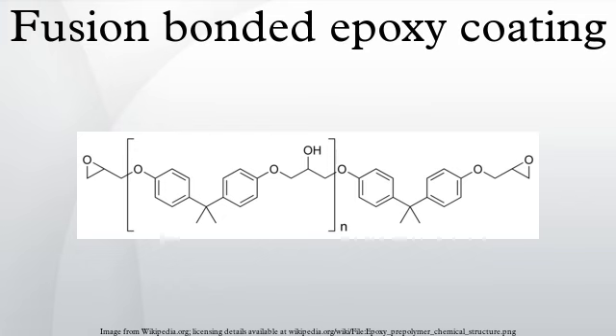Surface preparation: blast cleaning. Blast cleaning is the most commonly used method for preparation of steel surfaces. This effectively removes rust, scale, salts, etc., from the surface and produces an industrial-grade cleaning and a rough surface finish. The roughness of the steel achieved after blasting is referred to as profile, which is measured in micrometers or mils. Commonly used profile ranges for FBE coatings are 37 to 100 micrometers. Profile increases the effective surface area of the steel. The cleanliness achieved is assessed to ISO 8501-1 grades.